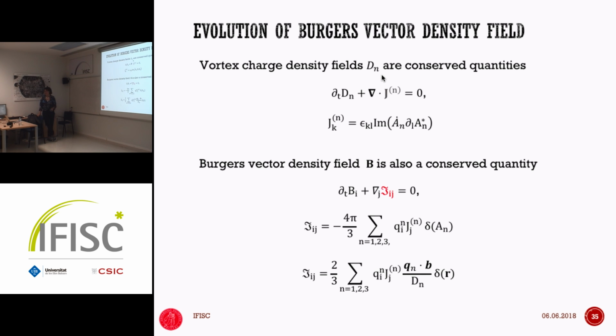And so we've been investigating this also in the spirit of topological defects, localizing topological defects as the zeros of the order parameter. And what we found out is that the velocity of the defect is directly related to the stress, and in a certain limit it is like the Peach-Koehler force. So these defects live in a stress field induced by the other defects. Each dislocation produces a stress field, and the dislocations interact with each other through the stress field. The question is whether the stress field is at equilibrium or not. Is this an elastic stress, or is it a much more complicated stress?